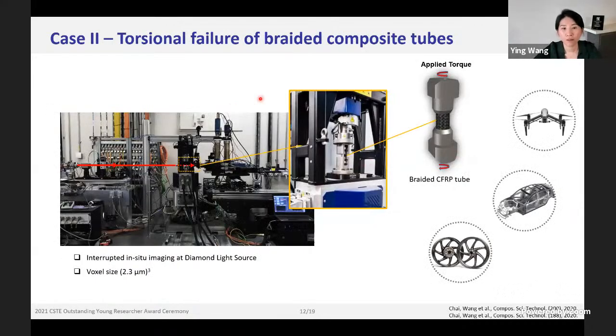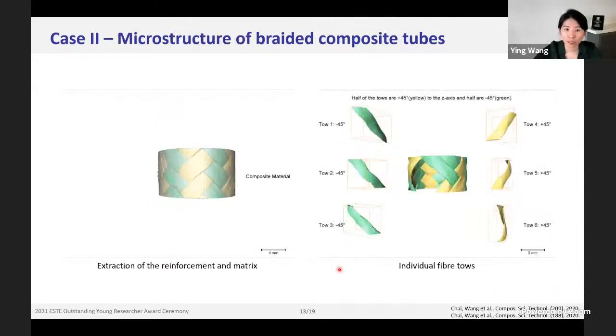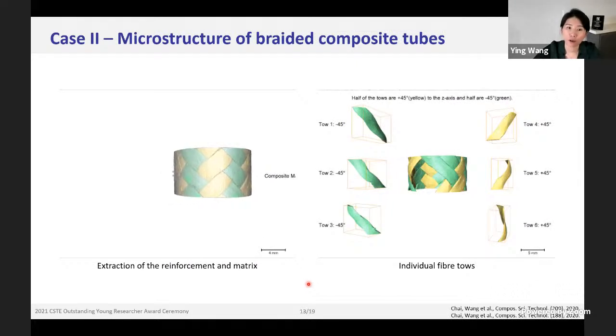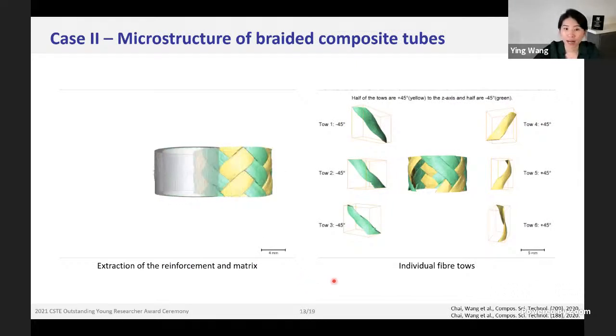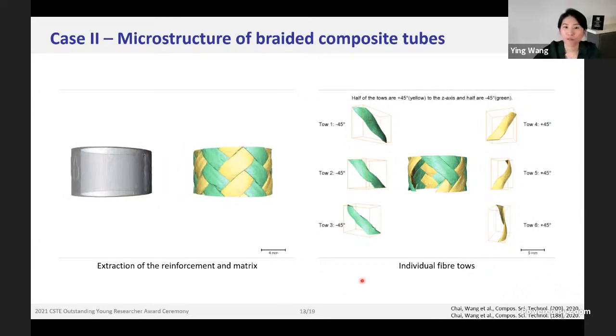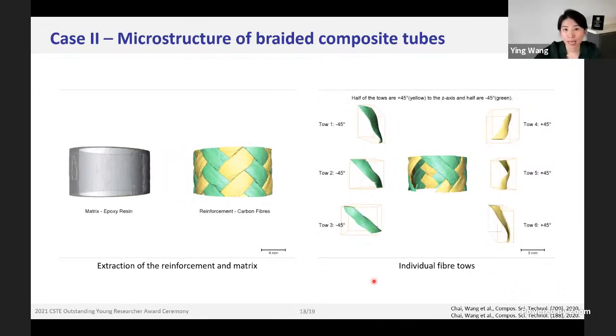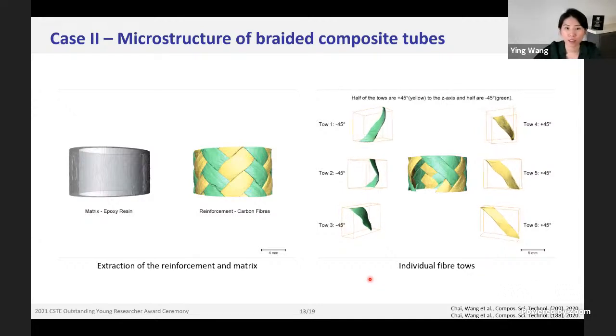Apart from simple loading scenarios like tension and compression, we also managed to do some torsional failure studies of braided composite tubes. And here shows the first in situ torsion study we did at the Diamond Light Source on braided CFRP tubes. Before loading, we managed to look at the microstructure of the braided composite and quantify the wavelength of individual fiber tows, which is really helpful for later when we study the damage and correlate the damage with the microstructural features.